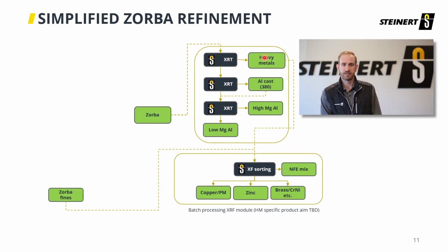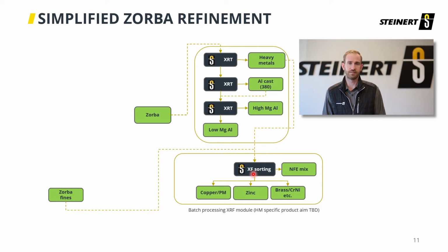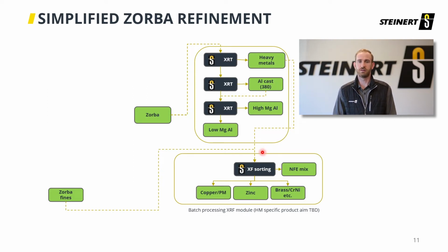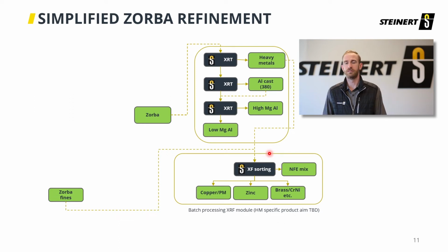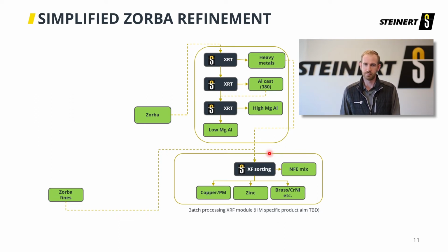When we look back at this heavy metal fraction that we produced off the first stage XRT, now this is going into your XRF sorting. Obviously, we covered earlier that XRF sorting is separation of heavy metal mix. So now you see the heavy metals going into the XRF sorting line. And at this point, you're doing commodity sorts. So you're looking for copper and precious metal. You may be sorting for zinc. You may be sorting for brass, chromium nickel plated, lead, stainless, etc. You can feed Zurik into this XRF line, and we're going to take a look at that. So this is a general layout of what refinement looks like from a flowchart standpoint, and this is really taking your typical recovery products, Zorba and Zurik, and talking about how we refine those further.